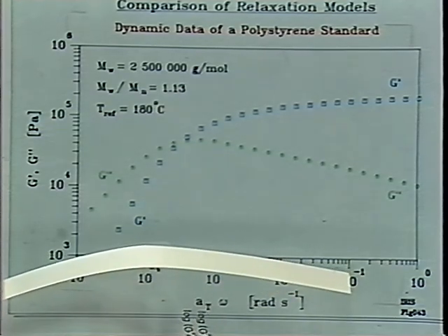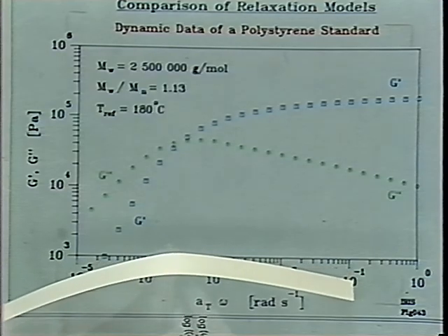But it's very hard to get good experimental data in the glassy region because your sample is out of equilibrium. When you lower the temperature below Tg, your coils are in a state which is not the equilibrium state. And then you measure G prime, G double prime in some out of equilibrium state which depends on thermal history, and you can get anything. So that's a real challenge maybe for you.